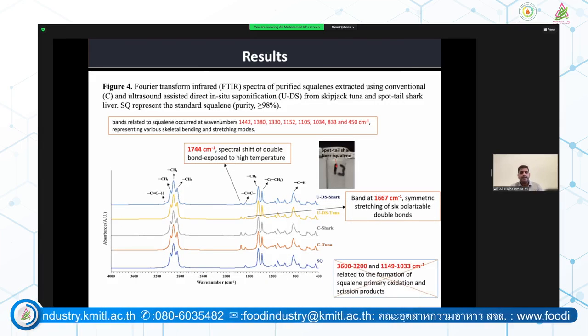And to determine the quality of the squalene we extracted, we tested the FTIR peaks and the bands related to squalene at various frequencies for its structural confirmation. We confirmed that all the bands are present in the FTIR pattern, and we could also see the band for the six double bonds in the squalene structure. We could see it is significantly present.